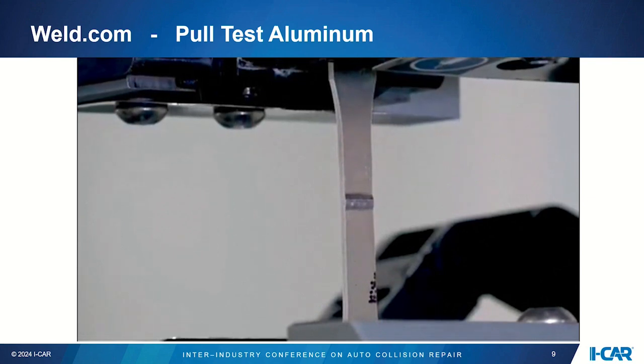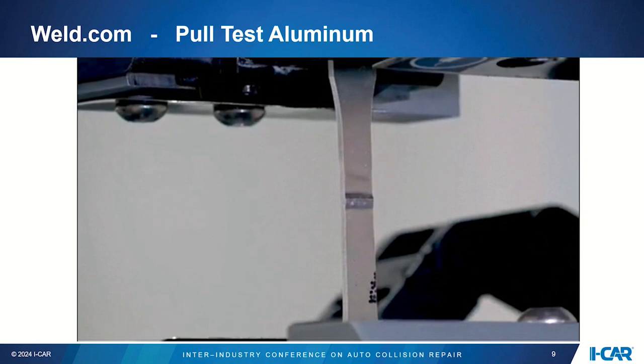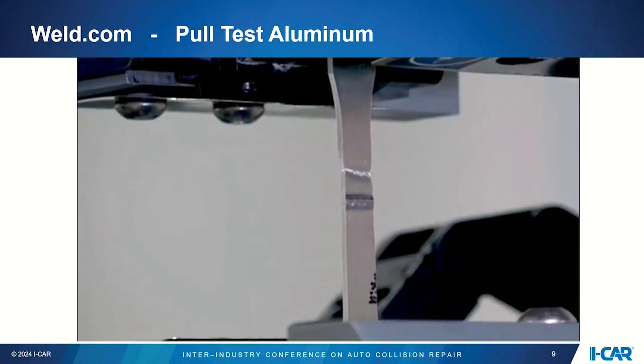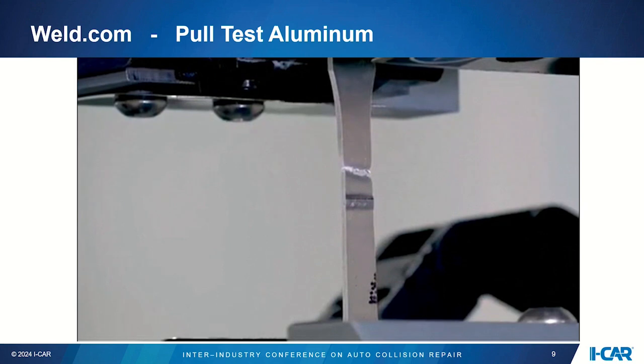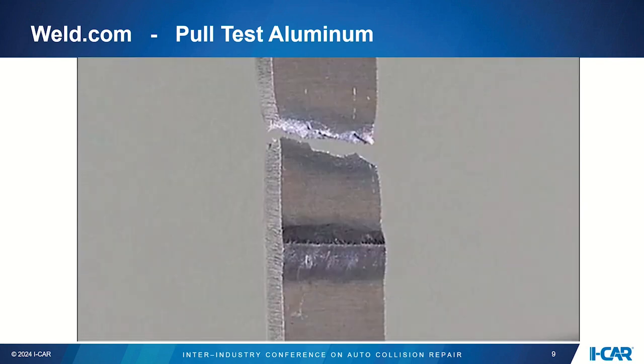On the video here, they're doing the pull test, and you can see where it breaks is not even in the heat affected zone. Right, and on a normal MIG weld, it would almost always break in the heat affected zone. Here, we're actually ripping the base metal apart before we're even touching the weld or the heat affected zone, if there is one.